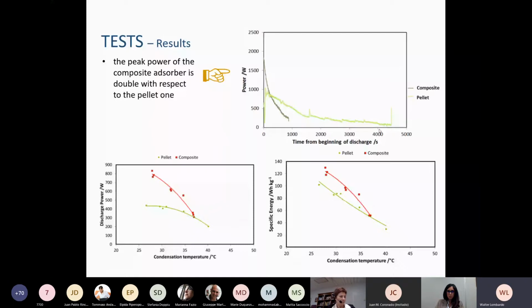Here we can see the trends of discharge power versus the condensation temperature, and also the specific energy, to make a comparison between the two solutions. We can see the composite presents better performance in the range between 27 and 35 degrees as condensation temperatures. So it can be taken as the best solution, and also for the specific energy.